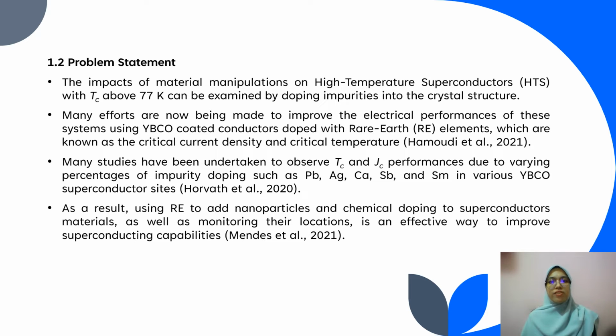Many studies have been undertaken to observe Tc and Jc performances due to varying percentage of impurity doping such as plumbum, argentum, calcium, antimony, and samarium in various YBCO superconductor sites. As a result, using rare earth to add nanoparticles and chemical doping to superconductor materials, as well as monitoring their location, is an effective way to improve superconducting capabilities.